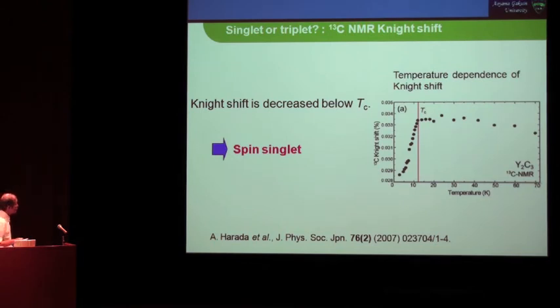After our discovery, I sent these samples to Kitaoka sensei's laboratory, and Harada-san got nice data. The Knight shift is decreased below TC. This material has spin, so-called spin singlet.